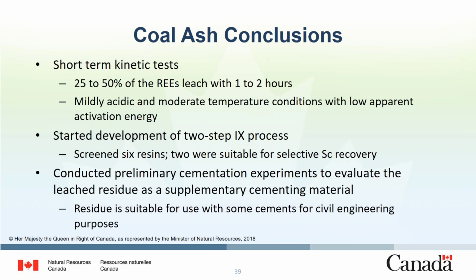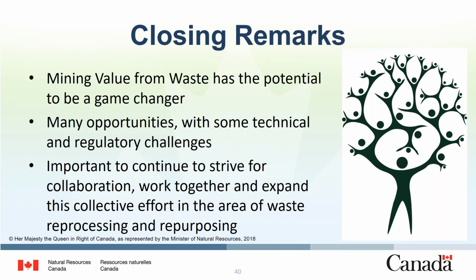We started the development of a two-step ion exchange process. We screened 6 resins and 2 were deemed suitable for further work. And we conducted preliminary cementation experiments to evaluate the leach residue as an SCM. And one of the residues performed quite well for several engineering purposes. And now I'm going to turn it back to Janice for her closing remarks.